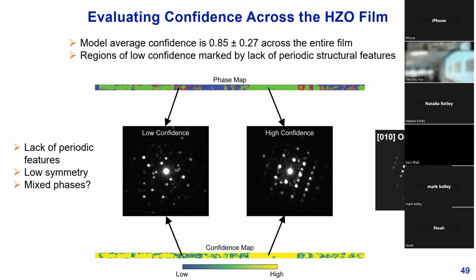We can see that some of these low confidence regions look like they're at grain boundaries between individual grains within the film, as well as at the interfaces between the HZO film and the top and bottom electrode films. However, despite all that, we can see that the average confidence across the entire film is around 0.85, which gives us really good confidence in terms of applying this model to further experimental data. And again, these regions of low confidence are mainly going to be marked by these low symmetry features that arise from having a mixed phase signal at these locations.